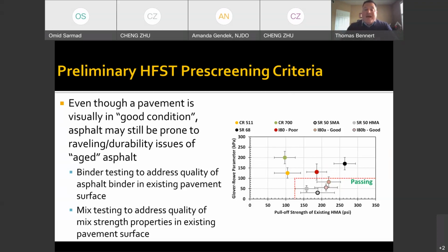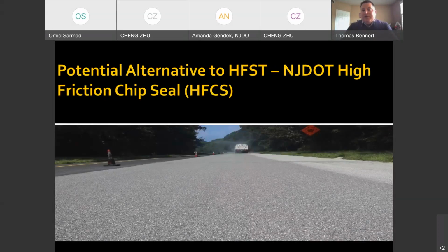So we have this now, this pass-fail area, as we continue to develop and take a look at some of these forensic studies. It does seem to show that this particular area in this performance space does an exceptional job at pre-screening pavements, whether or not we can use this HFST. And again, the major issue here with using the conventional HFST is the epoxy that's being used. These epoxy materials have a very high expansion and contraction rate when compared to asphalt materials. One of the things in this study was we thought, well, if the compatibility between the epoxy and the asphalt is not very good, are there some alternatives that we could possibly use?